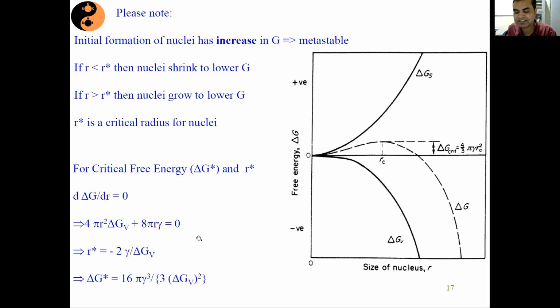Why is this important? This is not only limited to thin film. It is also applicable to nanomaterials. You will see that nowadays people talk so many things about nanomaterials. I prepared 1 nanometer size or 2 nanometer size. First of all, we will have to really understand whether that 1 nanometer size nucleation is stable or not. In my opinion, that 1 nanometer dimension or below is not going to be stable, just because your surface energy is way beyond your volume energy, and the total energy becomes positive, and that will make the whole thing unstable.